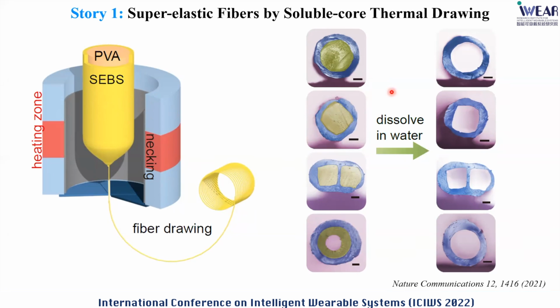And eventually, we demonstrated, for example, when we change the shape of the PVA, we will be able to fabricate those fibers. The beauty of the PVA is that after the fabrication process, simply by placing those fibers into the water, the PVA will disappear. So we end up with single material SEBS fibers. So this is the fabrication part.